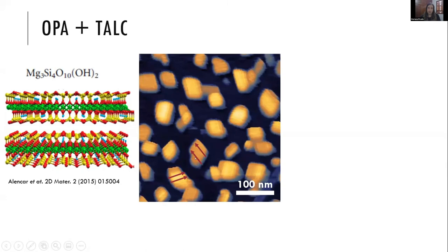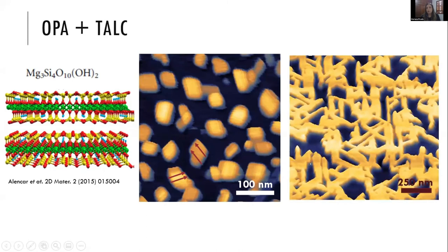We see both the formation of ripple domains, although thicker than before, but also these structures that are compatible with vertical bilayers of OPA in height. They exhibit some kind of hexagonal symmetry, which we don't observe for other phyllosilicates such as mica. This one is still undergoing investigation to better understand what's happening here.